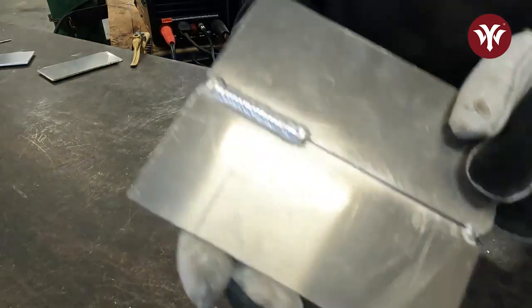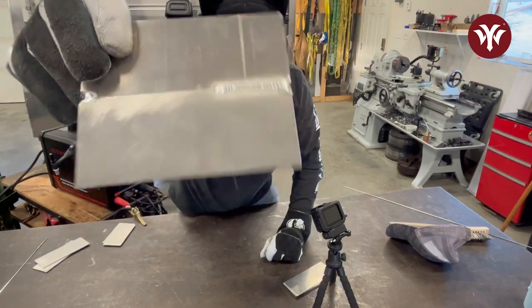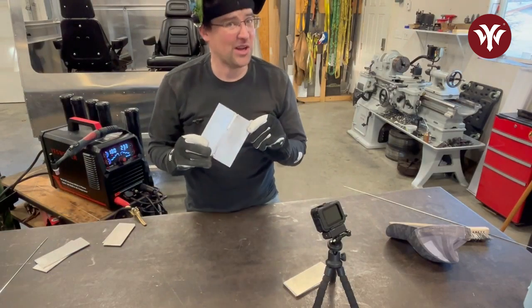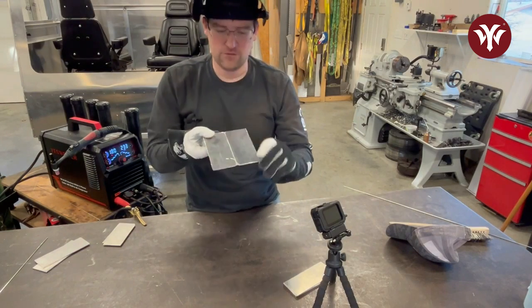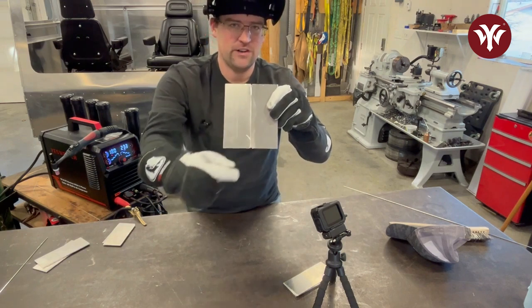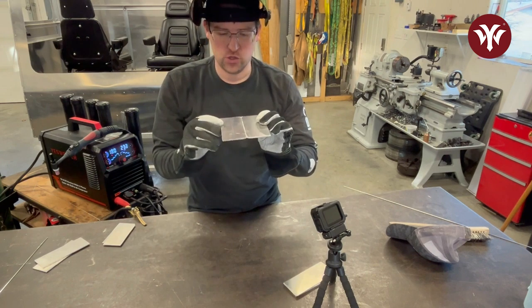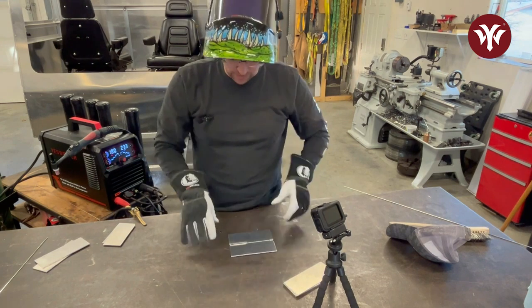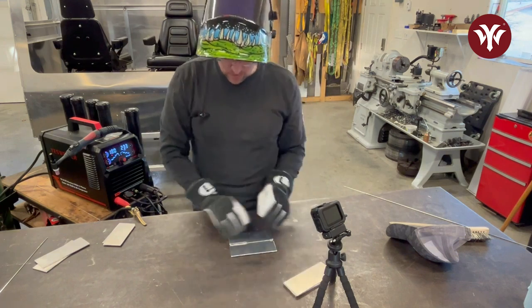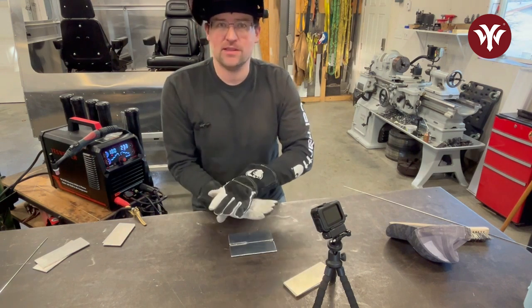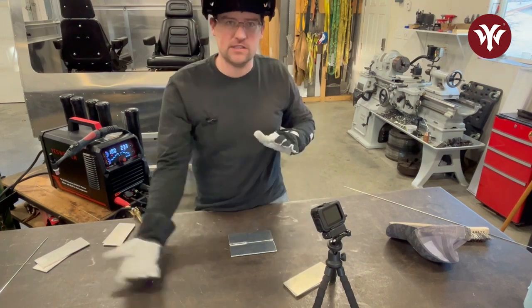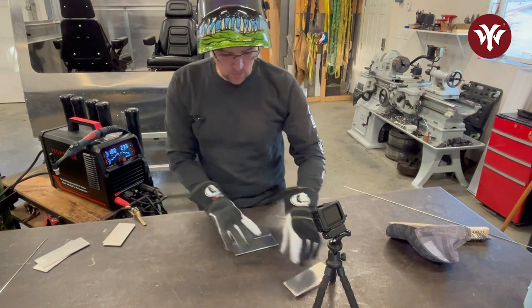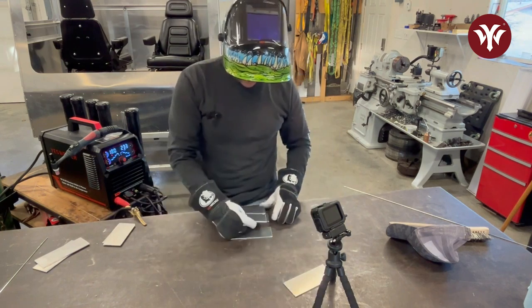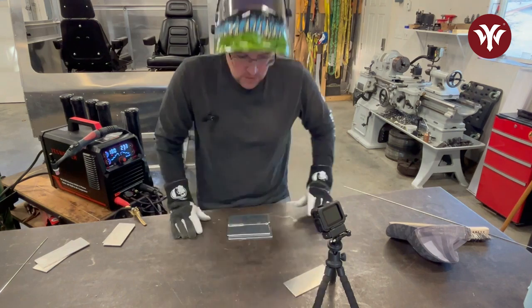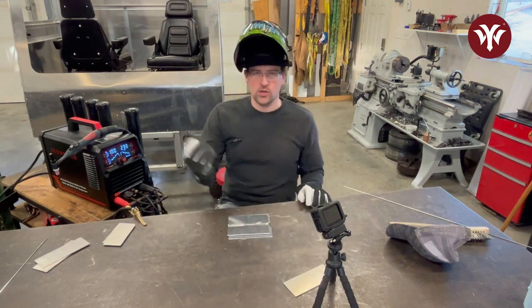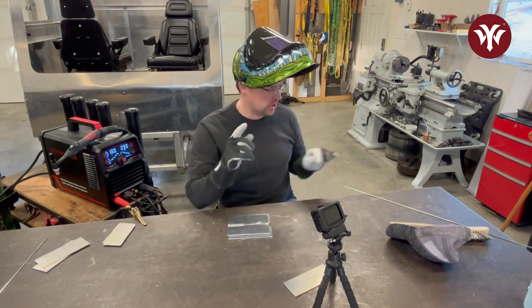All right, I'll show you there. The machine can weld really nice. If you notice the backside though, very little penetration. And I do believe that was largely to do with this table. Even though I got a molten puddle on top, the bottom side of that aluminum was getting all of its heat stripped away. So I want to go ahead, stack this off, and let's keep going, and I'll show you what that penetration on the backside should look like.